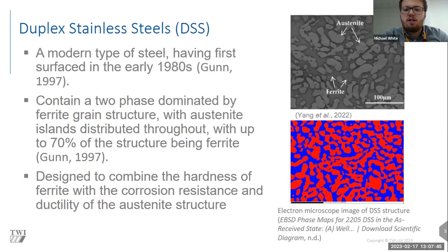Duplex stainless steels are a very modern type of steel, having only surfaced in the 1980s. You can see their structure in the electron microscope images on the right, displaying the ferrite grain structure with austenite islands present throughout. As mentioned on this slide, ferrite makes up to about 70% of duplex stainless steel structure, although ideally duplex stainless steels are usually approximately 50% austenite and 50% ferrite.